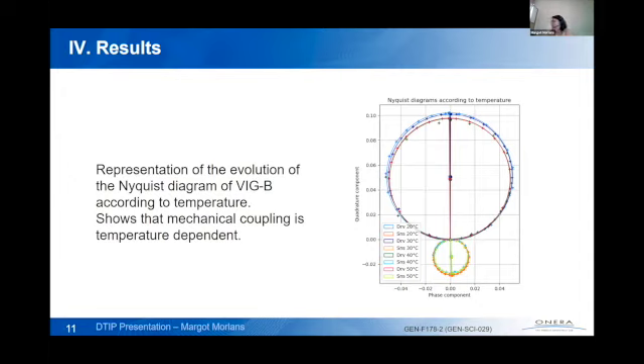This kind of diagram can also be used to do some temperature study, as shown here. We see that mechanical coupling is temperature dependent. In fact, at 20 degrees and at 50 degrees, the size of the sense circle is different. We can also determine the temperature dependence of the phase shift angle thanks to the axes of the circles. What's interesting to see is that we can track the temperature dependence of each parameter independently from the others. So that's really interesting for our future work.